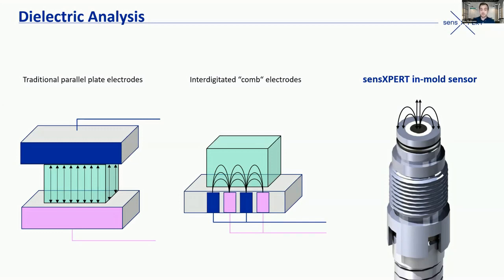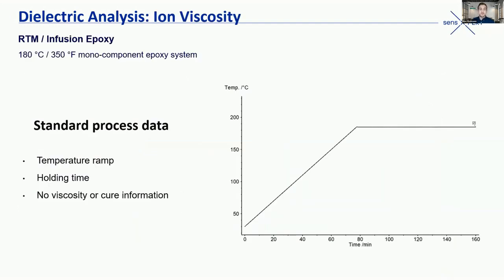And it's really durable, has a ceramic coating, so it's electrically isolated. We don't need any filters. We can actually measure, again, carbon fiber composites or other conductive materials and see exactly what's happening to the material during the manufacturing process. And so if we look at a really quick example, right, standard process data in RTM,